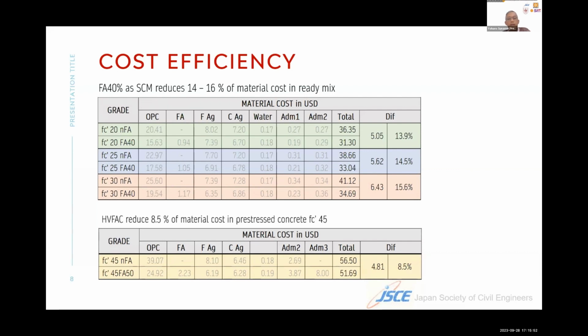And the second table, I will show the comparison on the high volume fly ash concrete that we use for the precast sheet pile. So we can reduce about 8.5% of material costs in pre-stressed concrete FC 45. So we can see the comparison. When we use FC 45 non-fly ash, the total material cost is 56.5 US dollars. But for FC 45 with fly ash 50%, the total material cost is 51.69 US dollars. So we can save about 4.8 US dollars, or about 8.5% of the total material cost.